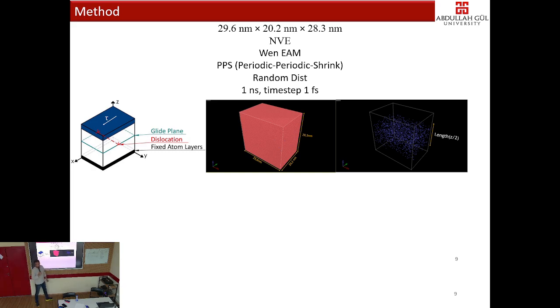So deciding this box size was a challenging part, and the dimensions we got are 29.6 nanometer in X. This axis, the Burgers vector line, is along Y. And 20 nanometer and 28 nanometer. So we kept the number of atoms, millions of atoms, volume and energy constant, and we use a Wen embedded atom potential proposed in the literature that can capture the repulsive effects of hydrogen too.